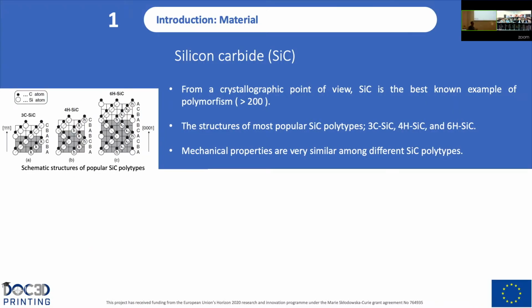So the material that we are using is silicon carbide. It's a ceramic material that, from a crystallographic point of view, is one of the best known examples of polymorphism, with more than 200 polytypes. The most popular structures of silicon carbide polytypes are 3C cubic, as we can see here, 4H hexagonal and 6H hexagonal. And the mechanical properties are very similar among different silicon carbide polytypes.